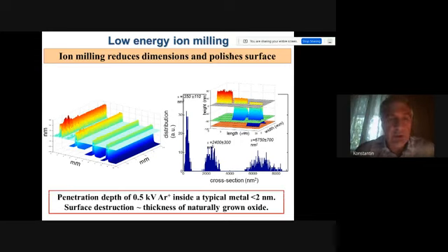These are AFM images of the same nanostructure, in this particular case aluminum. So on the left image, everything which is bright is aluminum. The blue surface is the original surface of the substrate, silicon. And after several sessions of ion milling, the cross-section of the aluminum part is reduced, and reduced. But of course, we also etch the substrate. So finally, we get a wall out of our substrate on which we have a very, very narrow line, which is our metal. Also, please note that inevitably there are always some imperfections.